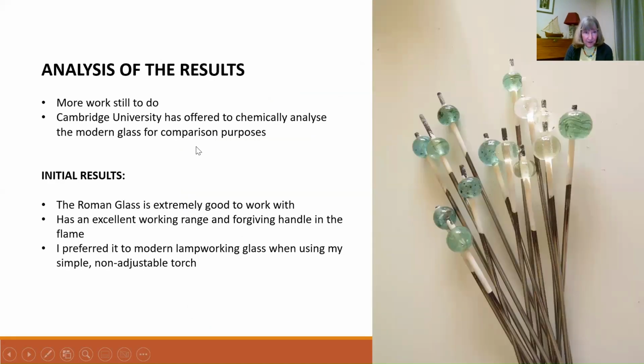So there's much more work still to do. Cambridge University has offered to chemically analyze the modern glass so that I can compare it, because the modern glass manufacturers don't like to publish their recipes, but if we can actually see the chemical content, then I can do calculations and compare it theoretically, as well as doing the practical tests. But the initial results show that the Roman glass is extremely good to work with. It's lovely. It has an excellent working range and a forgiving handle in the flame. And I preferred it to modern lamp working glass when using it with my simple non-adjustable torch. So huge sigh of relief. All my techniques seem very, very sound when using ancient glass.